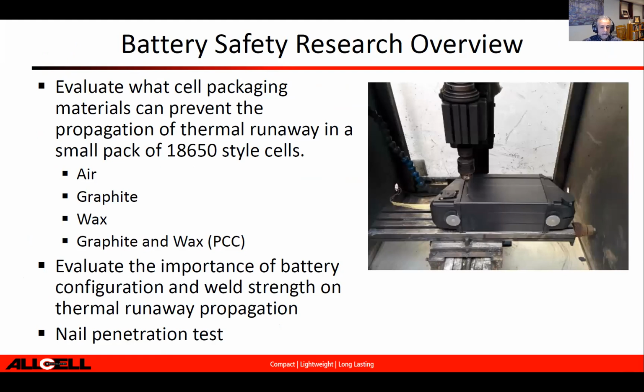goes haywire. We've developed significant solutions for those, and this is an example of a study that we did for a workshop at NASA a few years ago on a battery solution for electric planes, an aerospace application. What you see here is a battery pack of about 40 cells. It's commonly used in electric bike and scooter applications. We did a study looking at the impact of the material between the cells, or their passive thermal management. We tested packs with air, graphite, wax, and the last one was with our composite, which is a graphite wax solution. The idea here is that we put one cell in thermal runaway by nail penetration and then look at the impact across the pack and see if the pack can survive thermal runaway of one cell.